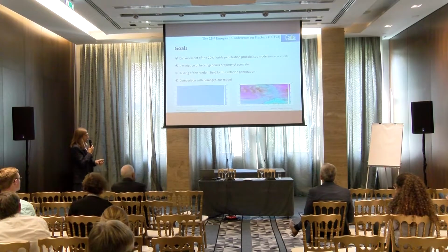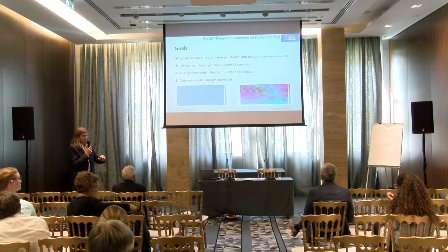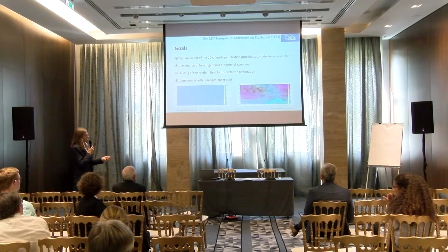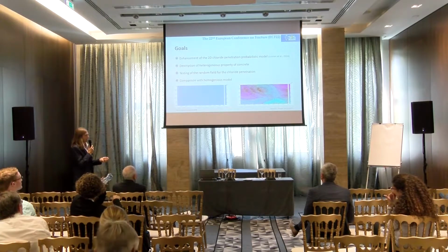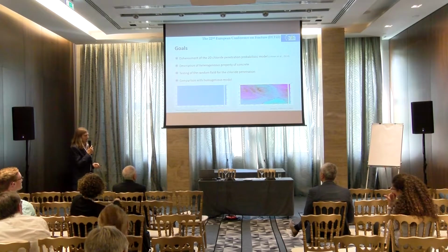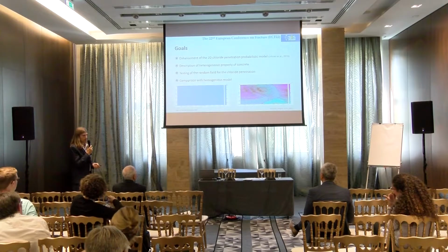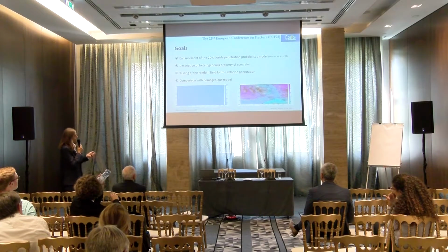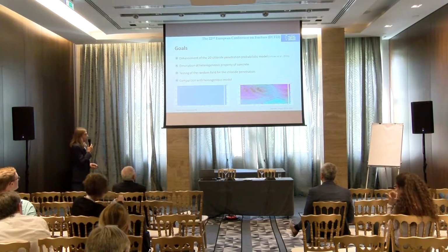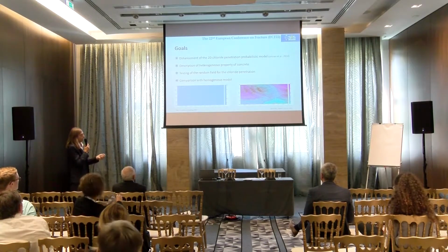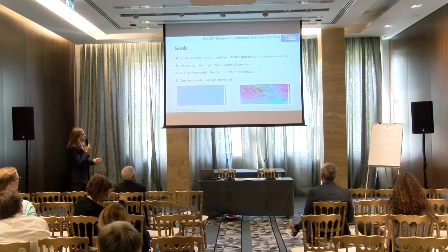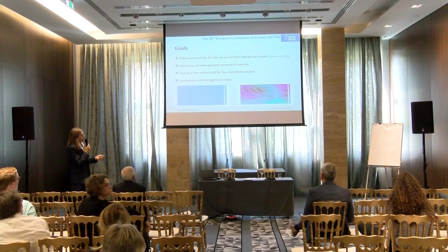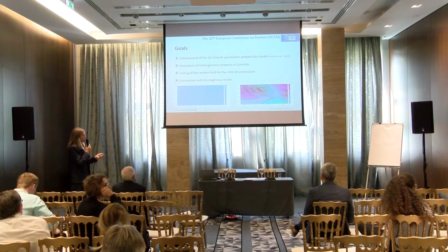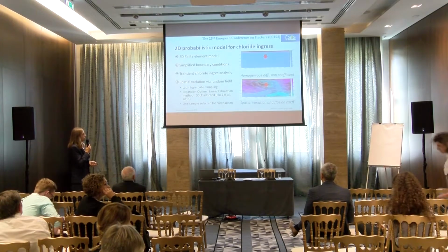And here you can see one Monte Carlo sample. Here is the homogeneous approach, material property, diffusion coefficient of chlorides into concrete, and this is the variation of the diffusion coefficient controlled by the autocorrelation. This is basically a random field. So we try to enhance the 2D chloride penetration model built in our collective, to describe the heterogeneous property of concrete, and initially tested the random field for chloride penetration.